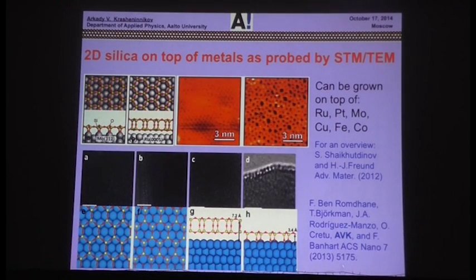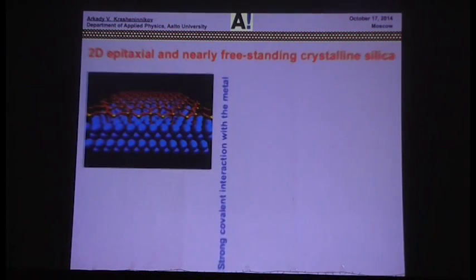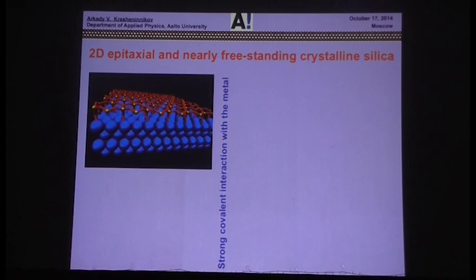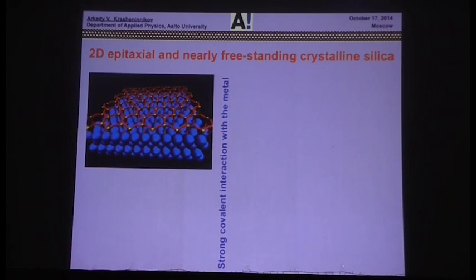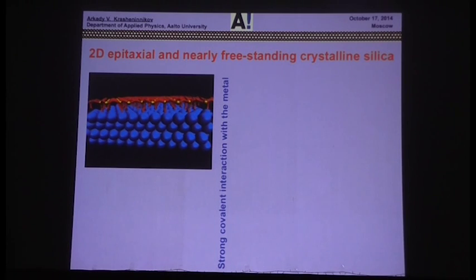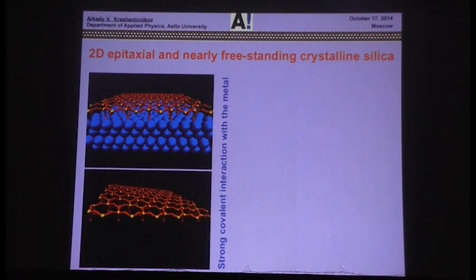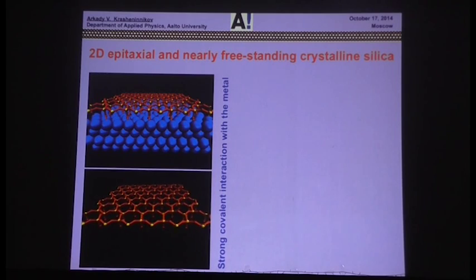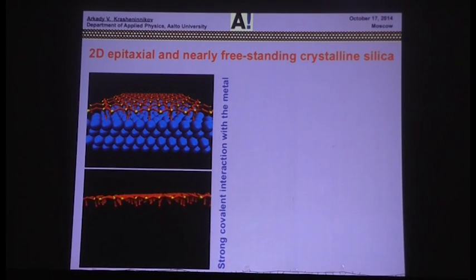So, together with Florian Banhart, we also looked at the structure of silica, epitaxial silica, and silica bilayer on different metals, which is a nice example of epitaxial silica, side view, I think, on cobalt. And actually, the next slide here is just some animation, to give you a better idea of what the epitaxial silica is, what you can see here, and this is just the same structure without the substrate. It's covalently bound to the metal surface, the interaction is pretty strong.